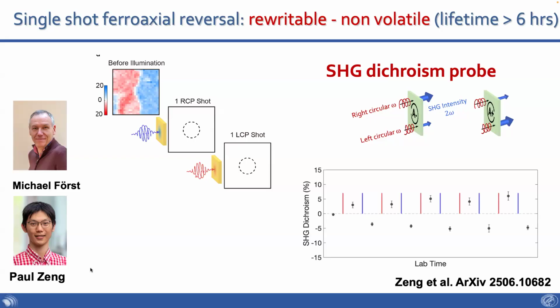And you can tell that this is very interesting because Nature didn't want to send it out for review. What temperature is this at? And that's amazing how long the lifetime is. Very, very good question. The temperature that it is at is below 190 Kelvin, but just below. 190 Kelvin is the thermodynamic transition temperature, and this is, I'm going to say, 90%. If you go far deeper, this thing gets stiffer and stiffer, and you can't switch it with these fluences anymore.